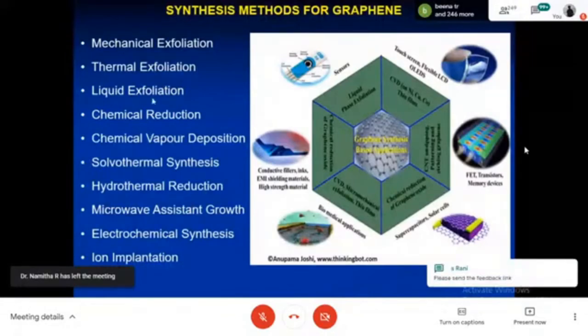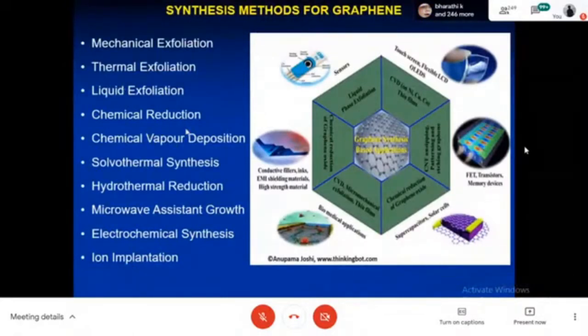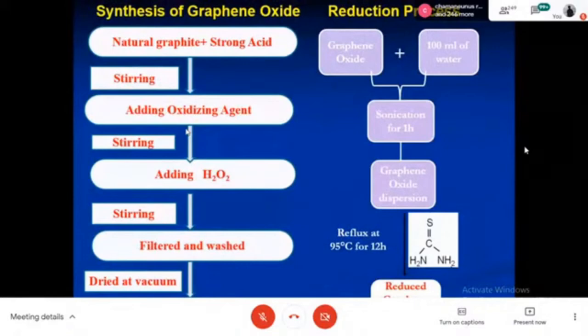Among all these techniques, the chemical reduction is the simplest method to make this graphene. So what we do is we take natural graphite as the raw material, and then mix it with very strong acids just to isolate the layer structure of these graphitic layers, and then introduce the oxygen functional groups by deliberately oxidizing, introducing the oxidizing agent. Then you have the oxygen functional groups introduced in that. Then you filter it, wash it, and then dry it in a vacuum, then you get the graphene oxide. So now you have the graphene oxide enriched with oxygen functional groups.